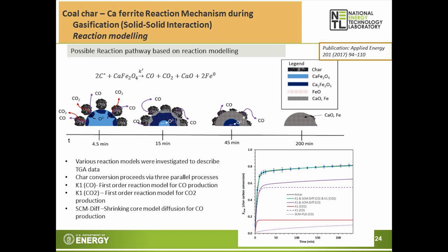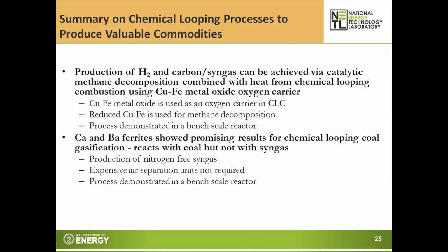So this controlled diffusion of oxygen through the oxygen carrier is the reason why we are getting more carbon monoxide than CO2. So, the summary of the chemical looping processes to produce valuable commodities: production of hydrogen and carbon, or syngas, can be achieved via catalytic methane decomposition combined with heat from chemical looping combustion using the copper iron metal oxide oxygen carrier. And also the calcium and barium ferrites showed promising results for chemical looping coal gasification. They react with the coal but not with syngas, so we can produce syngas from the reaction.